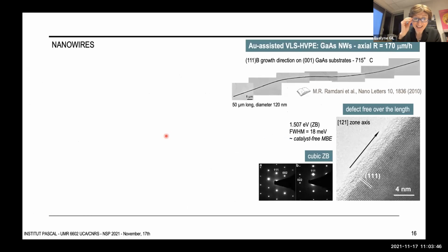Everyone knows, I guess, these results. The fast growth property of HVPE is maintained for gold-assisted vapor liquid solid growth of nanowires, here for gallium arsenide nanowires. They are grown at temperature higher than usual VLS growth as set up in MOVPE and MBE. Well, here HVPE opens the way to very long nanowires grown in short time processes, maybe for sensor applications, for instance.